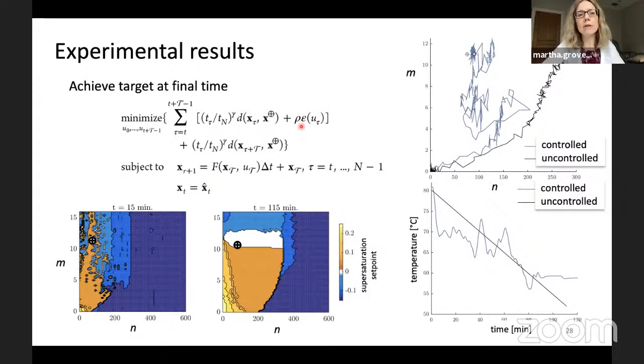Now our aggregate variables are the mass of crystals in this batch crystallization, which we measure with a REACT-IR for infrared absorption in the solution phase, and then infer the crystal mass. And then we have total counts measured from FBRM, and this is kind of a surrogate for number of crystals. But we're really just using these empirical measured parameters. We're not worrying so much about how they relate to the fundamental parameters. So this is really an approach driven by the data that can be measured by PAT.